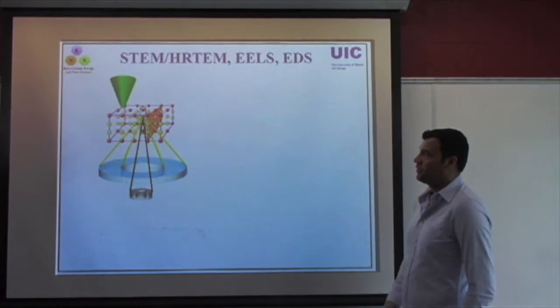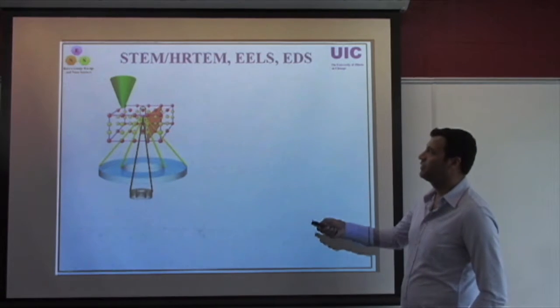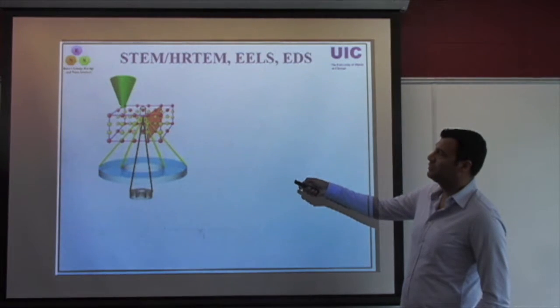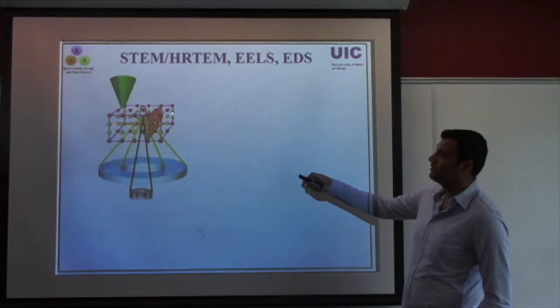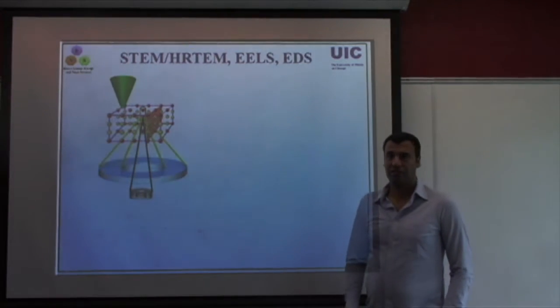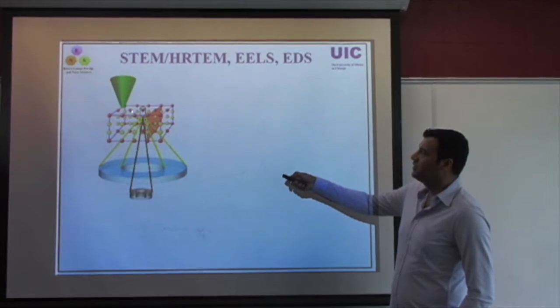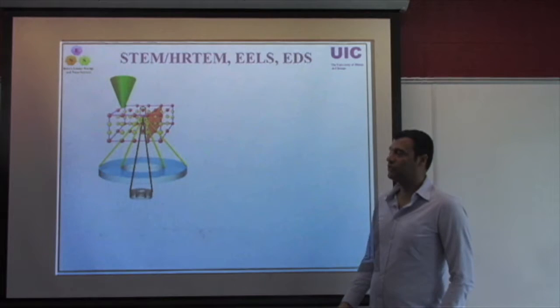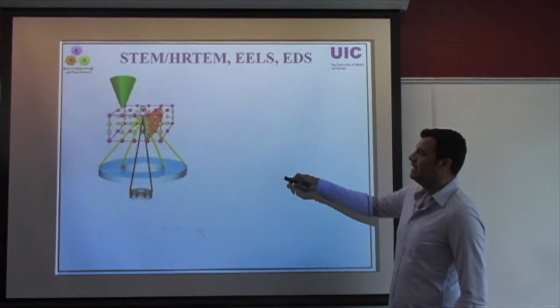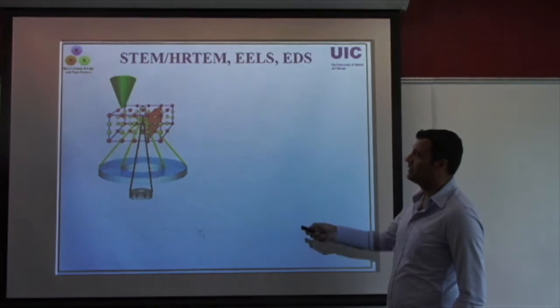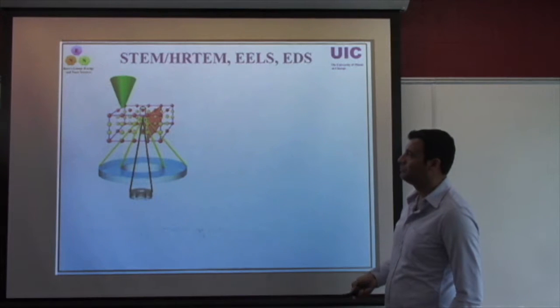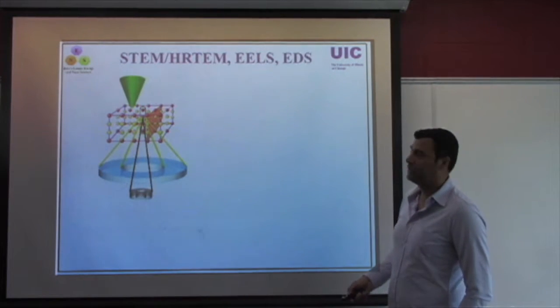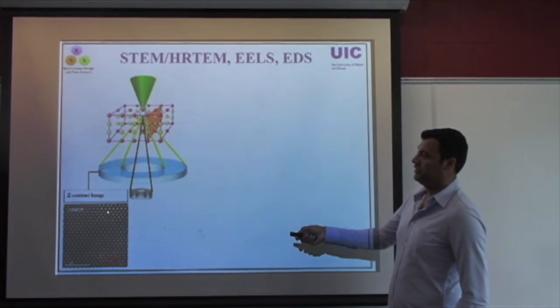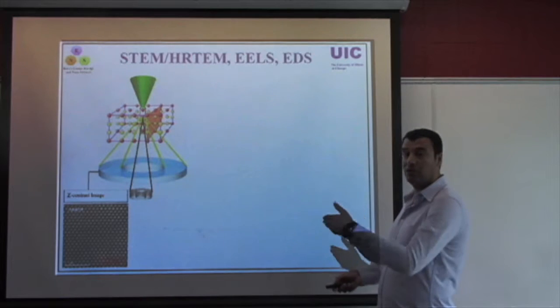So if you have an electron microscope, especially if you switch to a STEM configuration, it means that you convert your beam to basically a very small spot on the surface of your sample, and assuming your sample has some sort of crystallinity or even could be amorphous, then you're going to have scattering and change of energy of the electrons that are incident to this sample. And you can use detectors to image this atomic structure. You can raster it over the surface, and you can come up with images like this. You're going to see bright spots. It indicates the atomic column perpendicular to the screen.